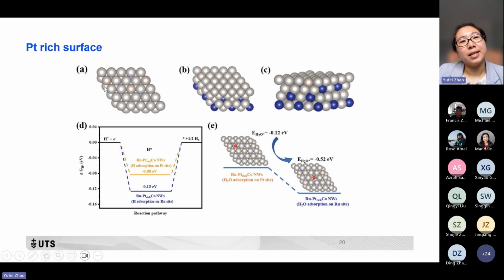And then we have conducted the DFT. The atomic structure we have set up here is with the platinum cobalt alloys inside, and the platinum surface. We can see a platinum-rich surface, and we have changed some atoms from platinum to ruthenium.